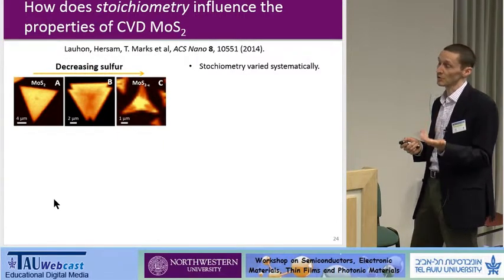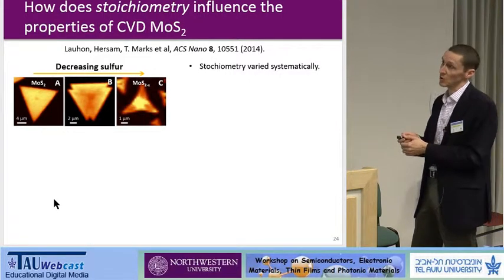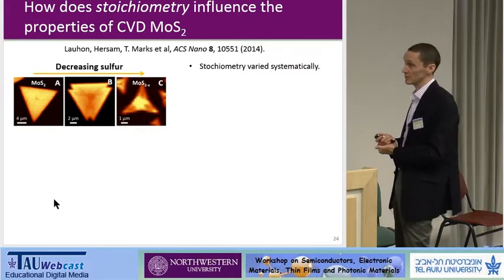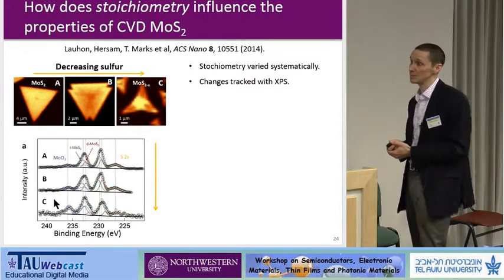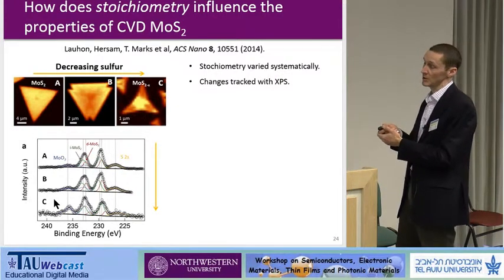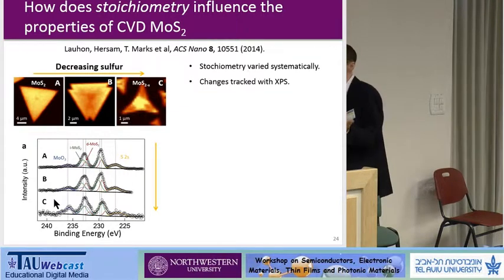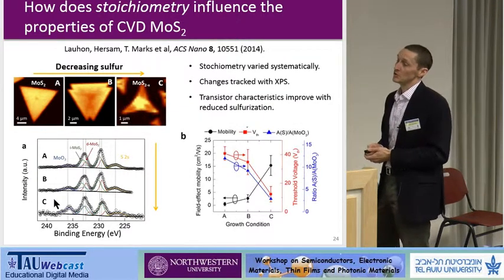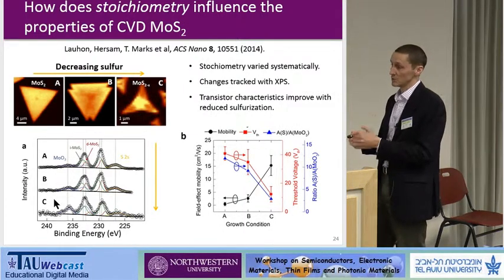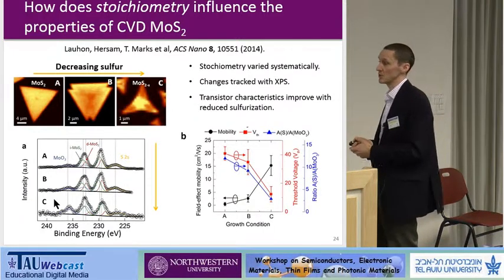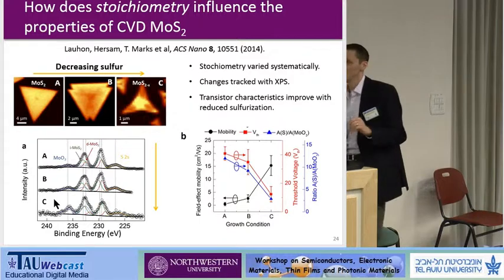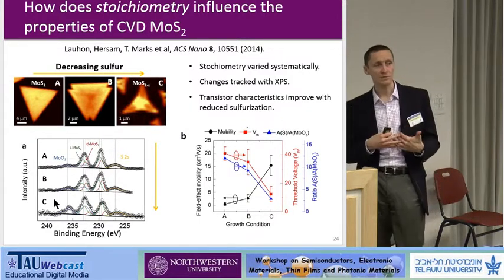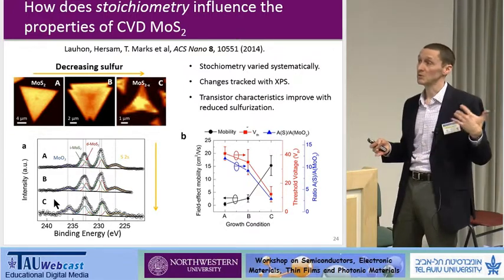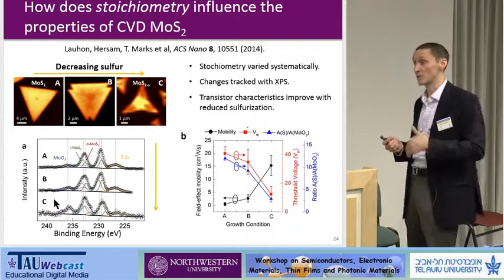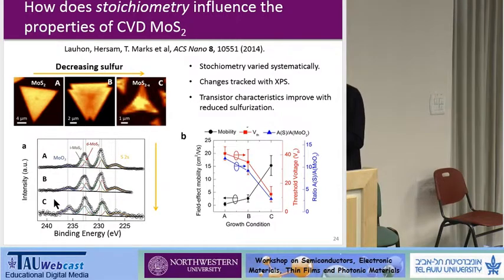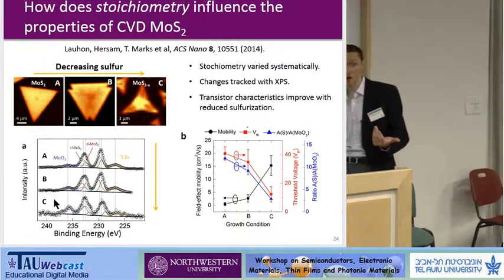So left to right, there are examples of MoS2 flakes from 3 different growths where we're decreasing the amount of sulfur exposure. If we look in XPS, there's a decreasing sulfur peak, which essentially corroborates or correlates well with the synthesis conditions of reduced sulfur. In transistors, if you focus on the black line here, we saw that surprisingly, at least at first, the field effect mobility increased with decreased sulfur content. Now, I'm not going to explain this in detail, but it arises from the fact that we still have a large number of defects in this material, and we believe that the sulfur vacancies effectively dope it so we can get above a mobility edge. Okay? So we're in the midst of really exploring the basic properties of the material.